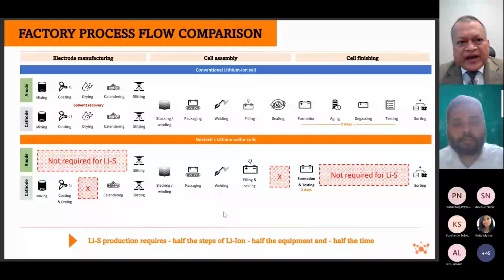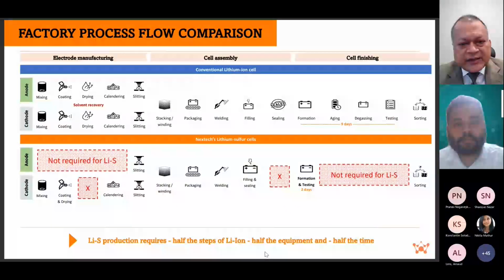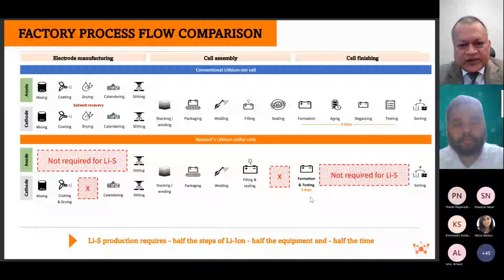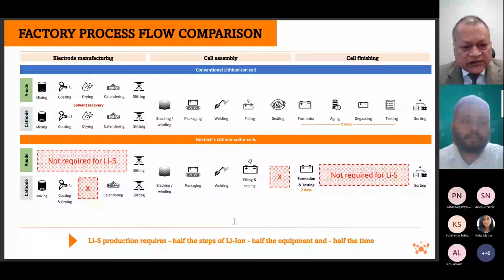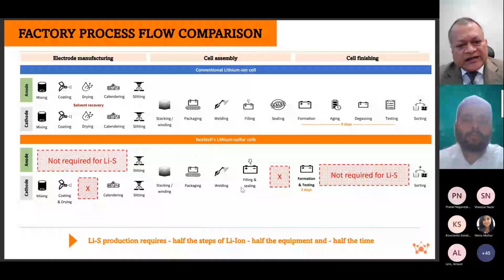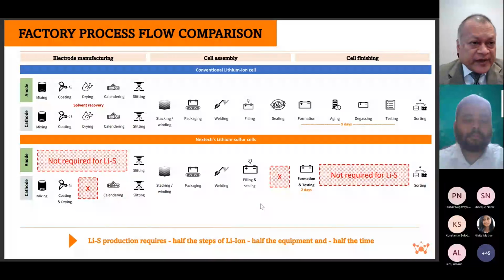You're looking at here a comparison of traditional lithium-ion battery manufacturing versus Nextech's lithium sulfur. You can see cathode, it's much simpler. We use water in our slurry making. And this is another area that you can improve quite a bit because sulfur being so light, it is amenable for dry pasting, especially if you use something like some electrostatic pasting, because you can